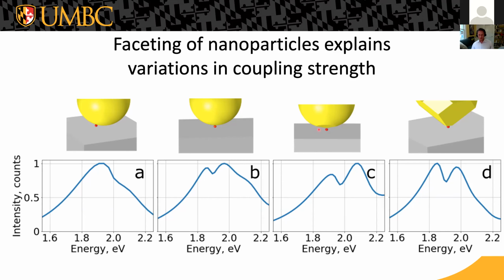So if we just put some facets onto the sphere and put the quantum dot either along the edge of a facet or at the vertex of multiple facets, we can see that this coupling gets stronger and stronger, and we get deeply into the high cooperativity and all the way into the strong coupling regime here. So what we're seeing is that the coupling strength is really very sensitive to the detailed nanometer scale structure of this plasmonic nanocavity that we're fabricating. And in this experiment, we don't have a lot of control over that kind of nanometer scale structure. We just have to look around and hope that we can find the ones that we're looking for.